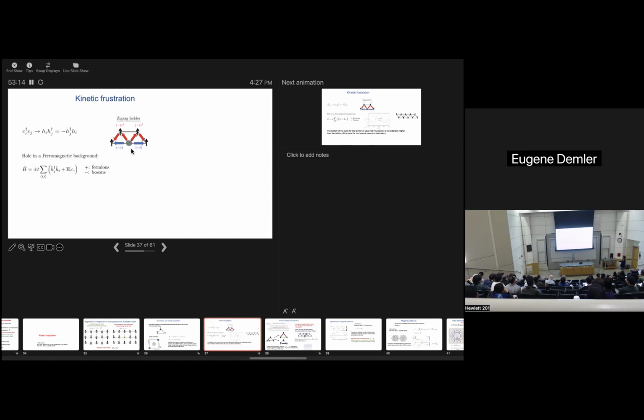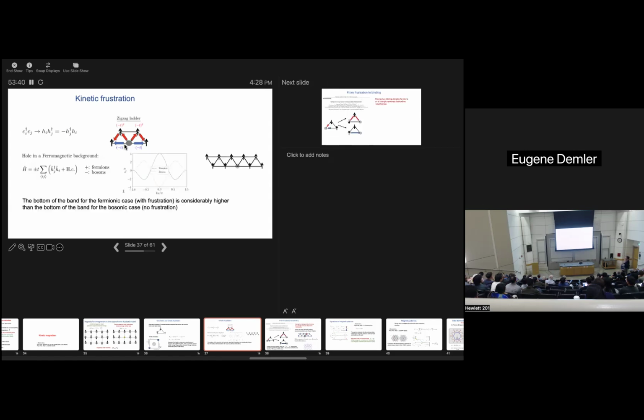And on the triangular lattice, this has a dramatic effect, because to go from this side to that side on the lower trajectory, we do a single hopping with the negative sign once, but to go on the upper trajectory, we do two hoppings with a negative sign, and the product of two negative numbers is a positive number. Therefore, the contributions of the upper path and lower path differ in phase by pi, and there is destructive interference. You can see this also just by looking at the dispersion of a single hole. Usually in the tight binding model, the bottom of the band is at minus t times the number of nearest neighbors. Here there are 4 nearest neighbors, so we would expect it at -4. But in fact, it's only -2. And that's exactly because of this frustration for the hole in the fermionic system.